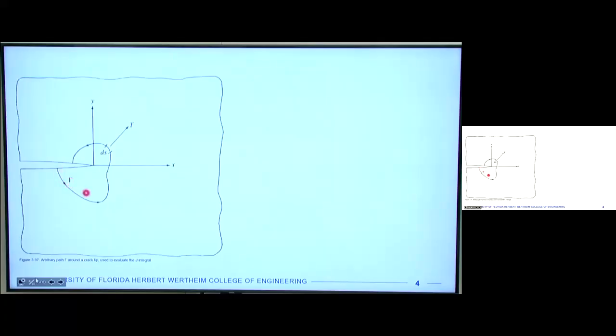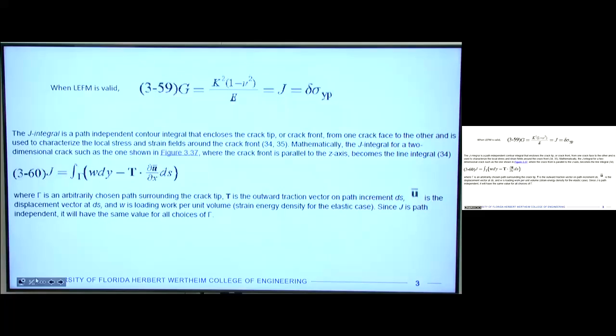And we'll represent that path by this uppercase gamma, a small, infinitesimally small portion of the path, ds, and then a force, in a lot of cases it's a traction force, so we call it T, on that little space there. And so the J integral is a line integral around that path, and it's a difference between the traction over those infinitesimally small things and the load work per unit volume, so what work is being done externally. And so if we subtract those two, we should get J, which should be equal to that strain energy release rate G.